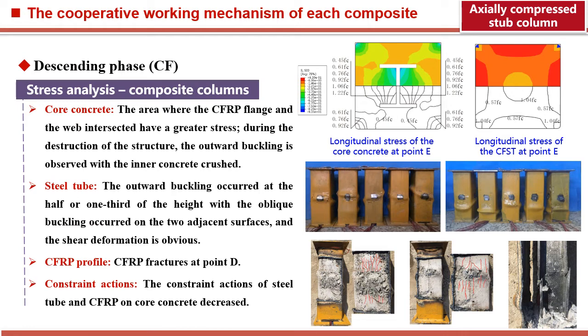In the descending stage, damage to the core concrete was found through analysis, and the damage gradually occurred from the edge of the constrained interface to the center of the section. Finally, after the core concrete is crushed, the profile is destroyed. Ideally, the method and order of the destruction of this material are exactly what we want. This is because throughout the destruction process, the three materials have given full play to the strength characteristics of each material.